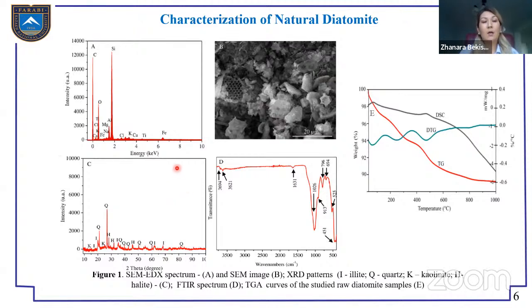The chemical elemental composition is on figure 1, and the main elements are silicon, aluminum, and oxygen, and a minor amount of potassium, iron, titanium, calcium, and magnesium. And the structure of natural diatomite in figure B, we can see numerous frustules with pores from 0.8 to 1 micrometers, and some laminated layers, particles of the clay minerals.